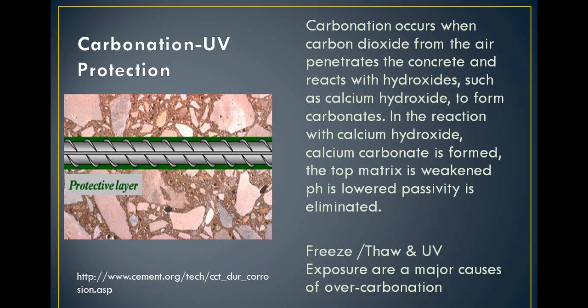Talk about rebar for a minute. You know, rebar rusting is really a product of overcarbonation of concrete. Inside the concrete matrix, the pH is about 11.5 to 12, and rebar can't oxidize there even if water gets to it. However, as concrete carbonates from the top down, it will lower the pH and allow for the rusting of the steel inside there. So by disallowing formation of bleed channels, you virtually stop overcarbonation of concrete. Freeze thaw and UV are major issues in this area, and we stop the negative impacts of that.